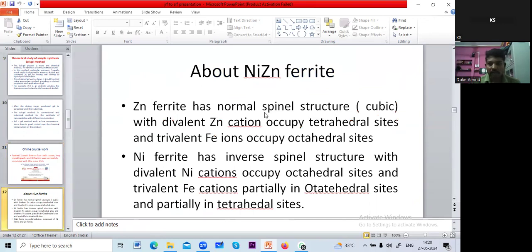Here, from some research papers, some literature review is taken about nickel zinc ferrite. Zinc ferrite is a normal spinel ferrite, cubic, with the divalent Zn cation occupying the A site and trivalent Fe ions occupying the octahedral site. Nickel ferrite is an inverse spinel ferrite with the divalent nickel cation occupying the octahedral site and trivalent Fe cation occupying the tetrahedral sites and partially the octahedral sites.